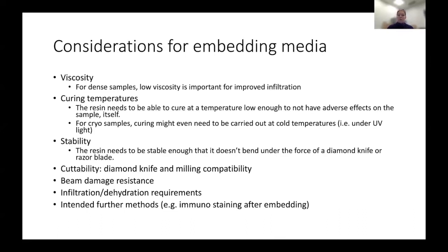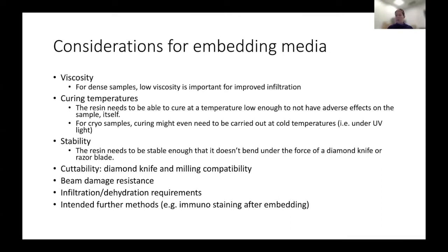For resins, you also want to make sure that it's stable. I'll talk in a minute about different formulations of EPON. You can mix up EPON hard or EPON soft or anywhere in between. There's a spectrum of hardnesses. You want to make sure that the block you end up with is stable enough, hard enough, that you can cut it and it's not going to bend under the force of a diamond knife or a razor blade. And even if you're milling, you're still going to want a hard block. You want to make sure that whatever your embedding medium is, it's compatible with a diamond knife or milling.